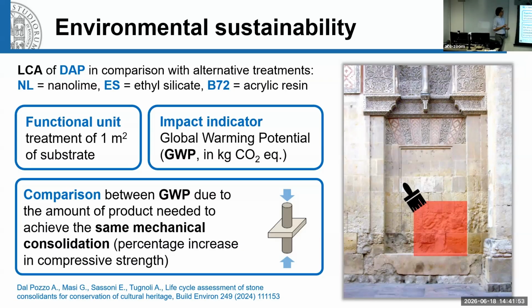So we decided to use as parameter to evaluate environmental sustainability the so-called global warming potential. I don't know if you are familiar with this. So the idea is quantifying the amount of CO2 that is linked to the production of the raw materials, the synthesis of the consolidants, transportation, application, and so on. Then again, to perform a fair comparison, we treated samples of marble, limestone, mortar, and so on, and we managed to evaluate the mechanical consolidation, mechanical effectiveness, so in terms of megapascals. So the idea is to compare products that are able to provide the same mechanical improvement.